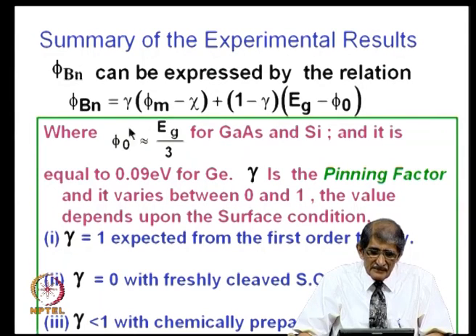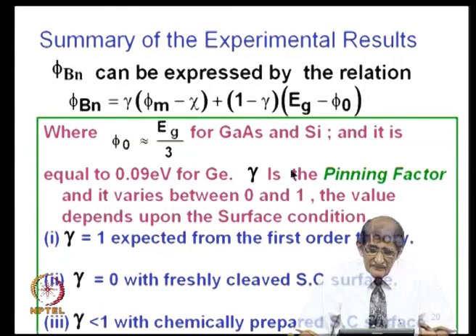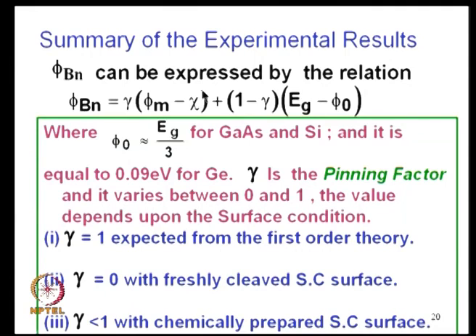When gamma equal to 0, the first term ideal theory is gone and 1 minus gamma equal to 1, Eg minus phi naught. So, we can say that when highly pinned surface, gamma was equal to 0, therefore, the first term went off and you got a term which is independent of phi m. Okay. What is that phi naught, we will see in my next discussion, and gamma in between the two. So, what we said is ideal theory, it is phi m minus chi, non-ideal theory, worst case gamma equal to 0 and it is independent of phi m and you get Eg minus phi naught. In between you get gamma less than 1. So, something like 0.5 times (phi m minus chi) plus 0.5 times (Eg minus phi naught), like that. So, in summary, that is what we are telling. You can express it in this fashion. The details of all these things, how it comes up due to the surface states or interface states, we will discuss in our next presentation, complete details of that, how to overcome some of these problems and how to use it, we will see in the next presentation.